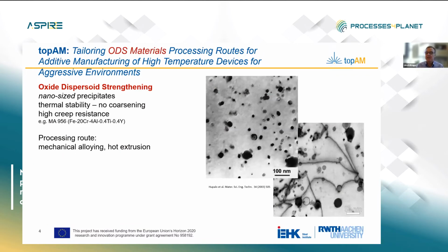High temperature stability can then be obtained by creep-resistant materials at these high temperatures, different from the approaches that were introduced before. We are aiming at ODS materials, so oxide dispersion strengthened materials. Oxide dispersion strengthened means we have to implement nano-sized precipitates, and they must be of very high thermal stability, so that they do not grow bigger during service at high temperature.